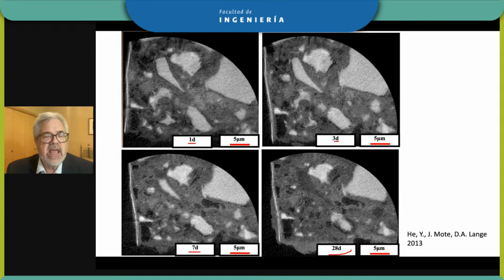And this is the same area of microstructure. So if you look at it, you see similar kinds of shapes, but there are some things to be learned by studying this. Look at this. That's a grain of cement. But look at it at 3 days, it's getting smaller. At 7 days, it shrunk quite a bit. At 28 days, it's gone. So this is the kind of evidence of hydration that we are very interested in.